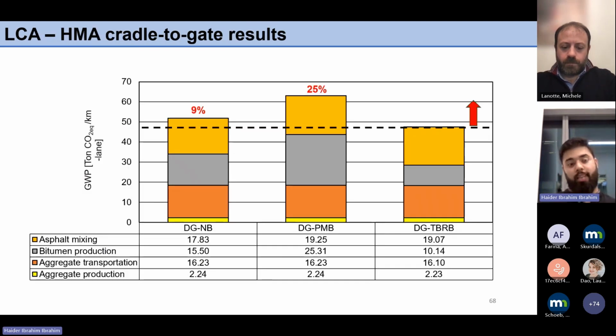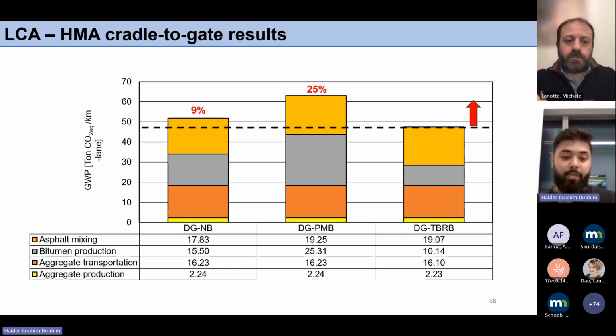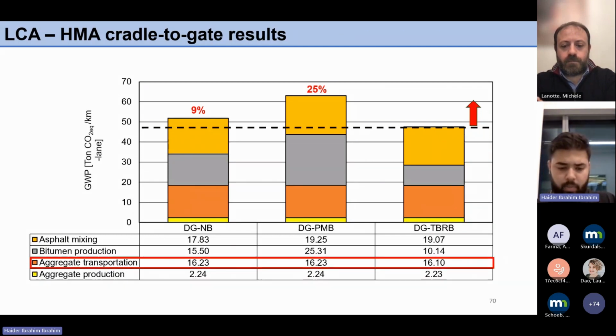If we look at the cradle-to-gate results, the DGTBRB shows 9 and 25% less environmental burden compared to the DG-NB and DGPMB respectively. The aggregate production and the aggregate transportation is almost the same across scenarios, but you can see that the DGTBRB has lesser amount of burden for the aggregate production and transportation. It's due to the fact that per kilometer, the DGTBRB, based on the volumetrics, has around 5 tons less material needed in a kilometer length of road.